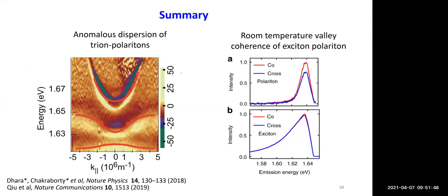And although the polariton's excitonic component will undergo a lot of depolarization and dephasing processes, the photonic counterpart, which these half-light, half-matter particles are made of, they basically offer a fast population decay channel, and this preserves the optical valley coherence. And this kind of room temperature polariton device can provide opportunities for valley-based switching architectures, for example, and they can also provide potential to other valley-polaritonic circuits.